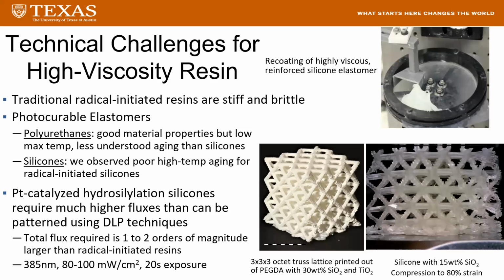We have previously investigated UV curable silicones with a thiol-ene radical-based curing system, but we observed pretty poor high temperature aging with this chemistry. So we are instead looking into adapting the traditional method of curing silicones, namely a platinum catalyzed hydrosilylation reaction, to be UV curable. There has been some work using UV to cure these types of systems, but it's been using relatively low intensities with curing times on the order of minutes, preventing its use in AM.